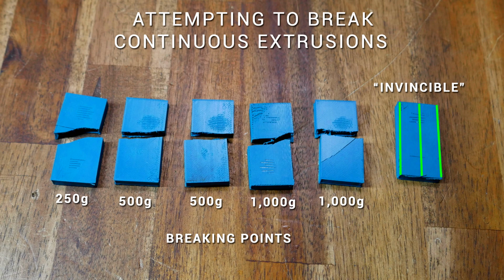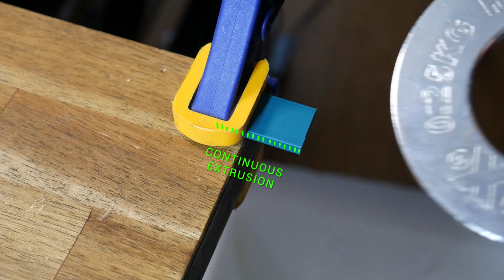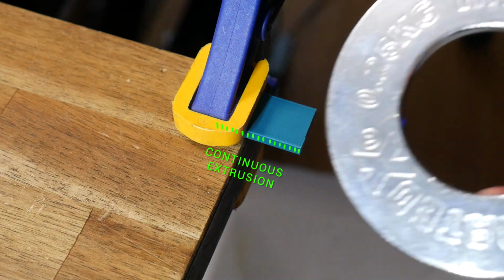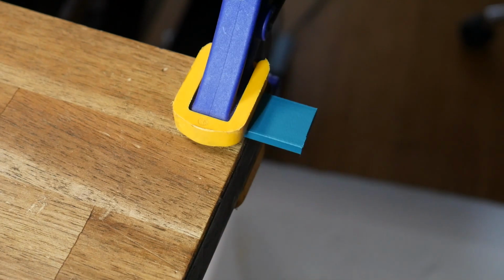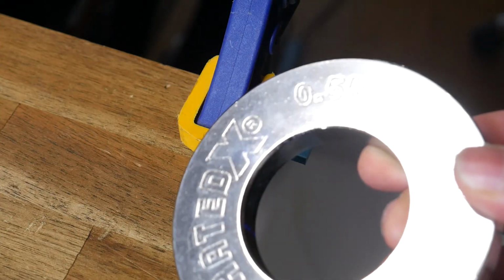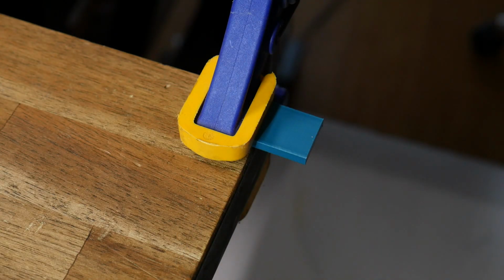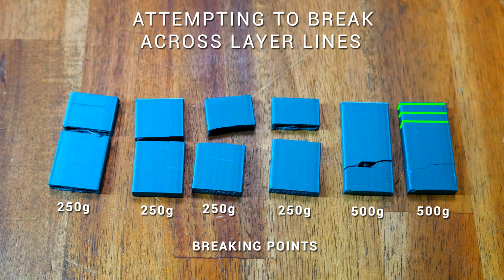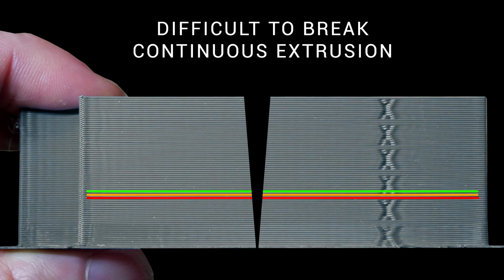So how about our other samples where instead our extrusion is going across the part and we're effectively breaking apart the layer lines? I used the same testing procedure, starting out with 250 grams and then increasing that to 500 grams as necessary, stopping when a failure was reached. And as you can see from these results, the parts printed in this orientation are significantly weaker than those printed lying flat on the bed. Just like the timber, our portions that were created continuously are quite hard to break, but those that have been stacked later on are much easier to split apart.